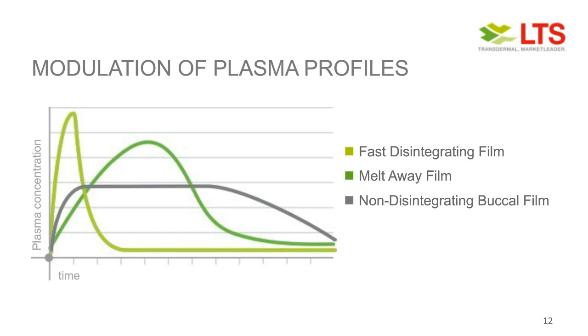So the first one, the fast disintegrating film, is tailoring a short Tmax, a high Cmax, really fast onset of action for episodic treatment to have the patient as quick as possible in the medication. The second type, the Meltaway films, are really trying to reduce the Cmax very often, as said before, to eliminate side effects, for example, and really focusing on the improved bioavailability, so it's a bit more prolonged pharmacokinetic profile. And the third, non-disintegrating buccal films, is really more constant delivery to the area, as mentioned before, over a certain time period.